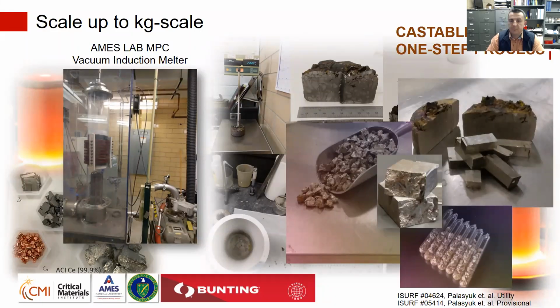It was successful. In fact, we were able to produce our material in a one-step process, and we were able to scale up to 2 to 2.5 kilograms. So the process is done in a vacuum induction melter in our Ames Laboratory Materials Preparation Center. And as you see in the central image, you see the look of the alumina crucible after the synthesis. In fact, we have proven that this alumina crucible can be used repeatedly with similar results.